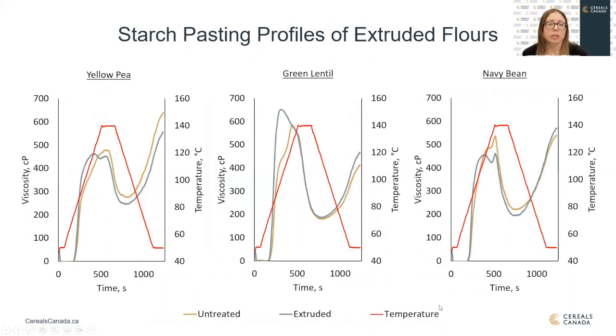We also looked at the starch pasting profiles. For this activity, we had the opportunity to test these on a high temperature RVA. So we used a 140 degree Celsius starch pasting profile. And we did that just because it was giving us better discrimination between the untreated and extruded flours, so we could see more differences. So for each of the pulse types, the extruded sample peaked earlier than the untreated sample. This could be because of that slight increase in starch damage, because the damaged starch granules will uptake that water more readily.